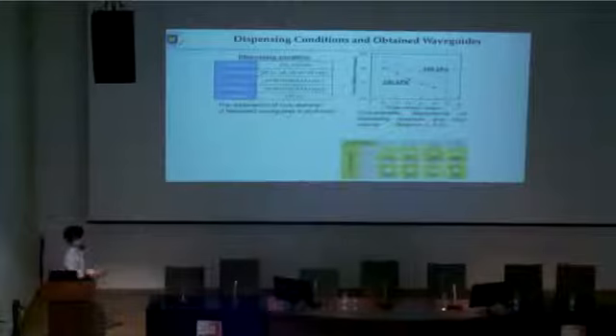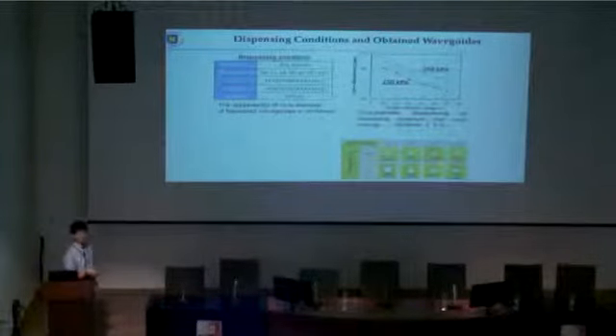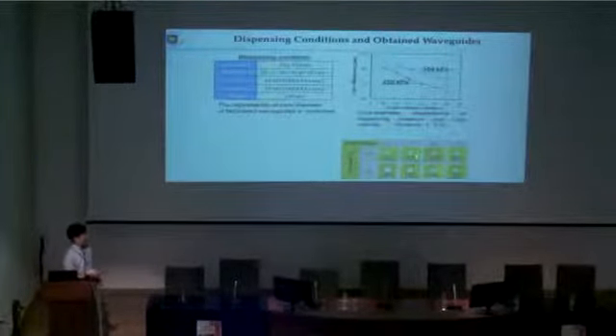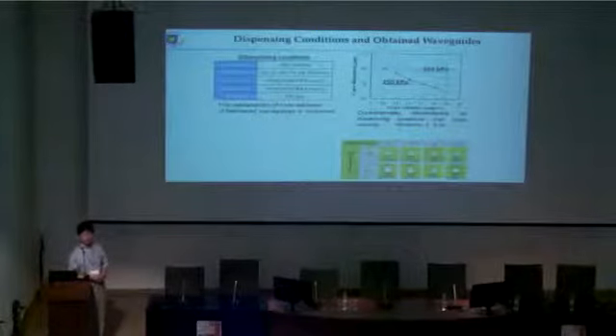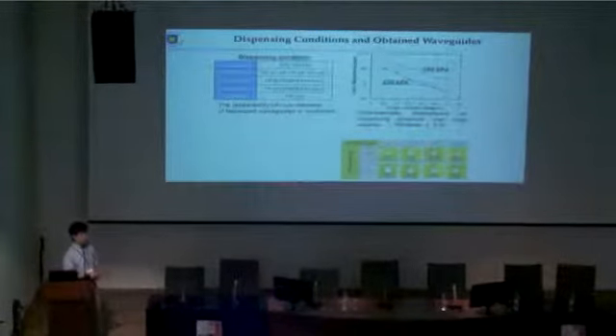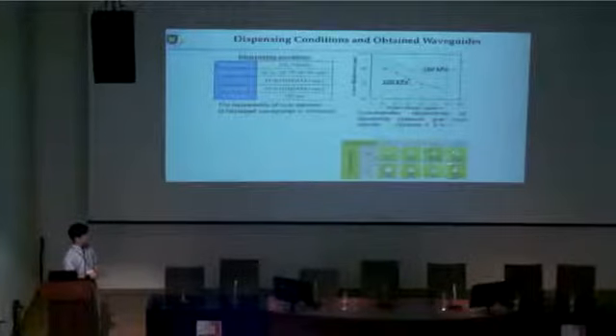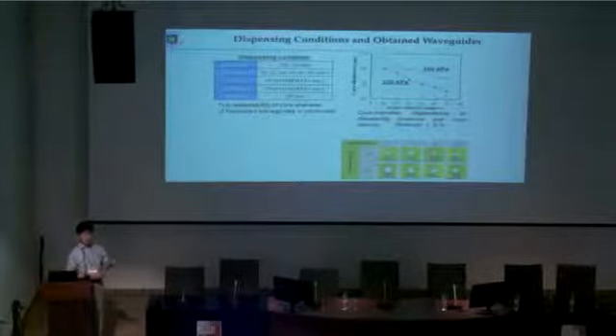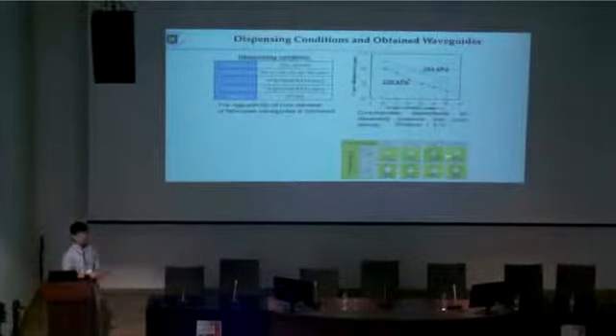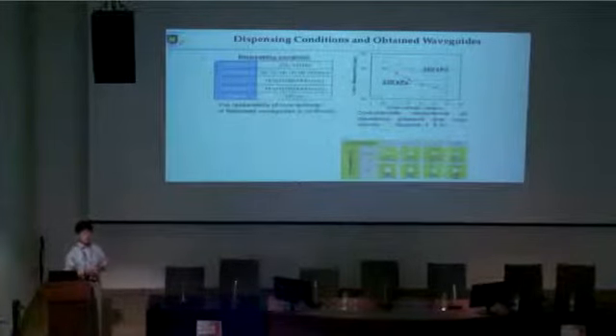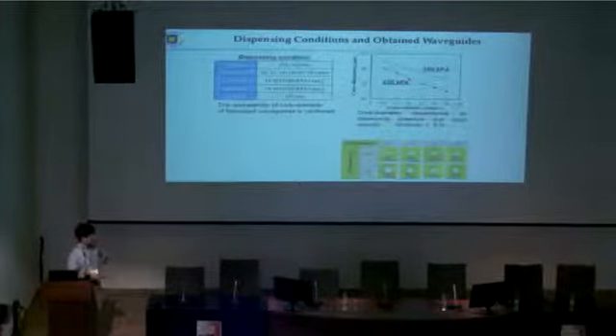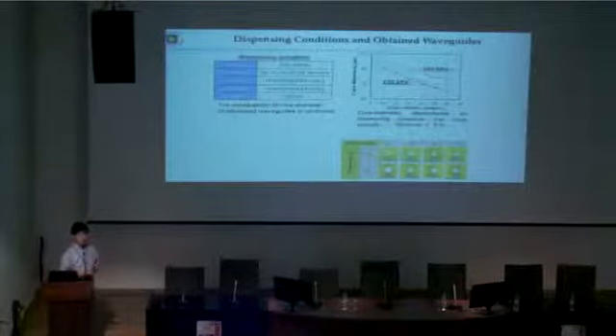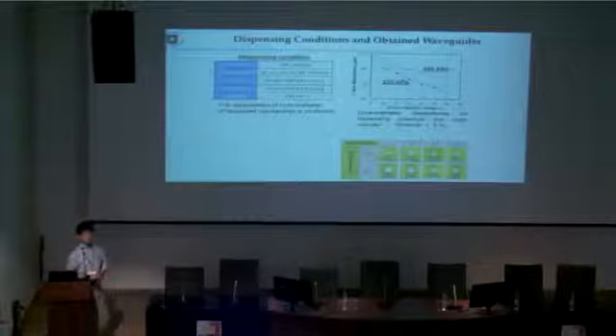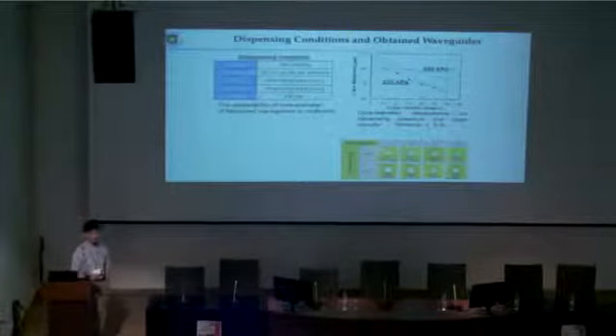The core diameter we showed, for example, is just measured from photos taken by the microscope. And as you can imagine, the contrast is very important between the core and the cladding. So some deviation of the core diameter may be included in this observed core diameter.